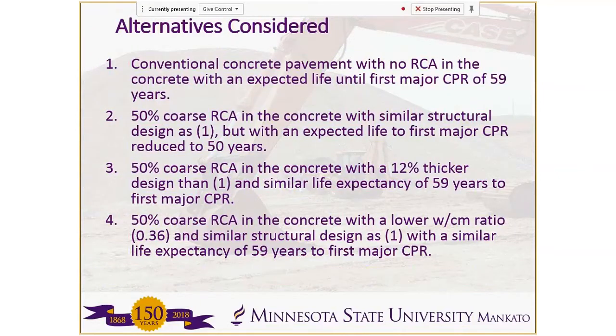So for this economic analysis, we looked at 4 different alternatives. Number 1 was basically our control, conventional concrete pavement without any RCA. Based on our discussions with some MnDOT personnel and experience, again, remember those pavements in the 1980s were built with a much higher water cement ratio. Nowadays, typically, we're using much lower water cement ratios. So the expectation was that these should be able to go a long period of time before needing a major CPR. So we assumed 59 years until the first major CPR.